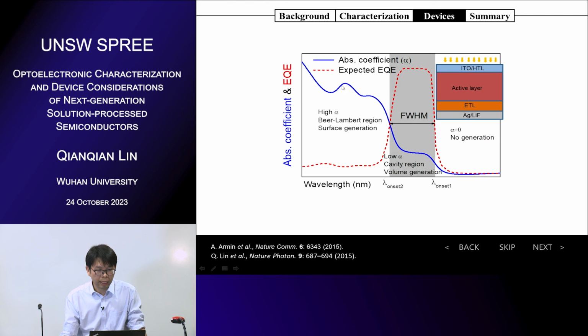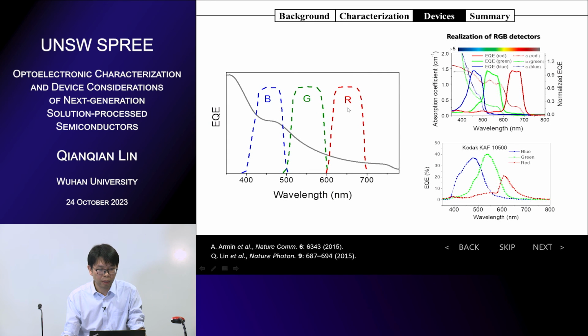So you will not get any photo response from the high alpha region, and you can get relatively higher photocurrent from the long wavelength region, and you do not have any absorption after its absorption tail. If you can tune the absorption spectra, you can tune the photo response spectra of the devices. So this is the idea of our RGB devices, and we first achieved it based on perovskite materials, and we got 3 devices, and we compared with commercial photodiodes, and ours have much better, sharper onsets. This is from Kodak, and this is our real devices.